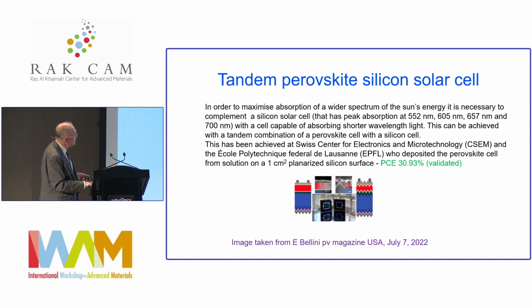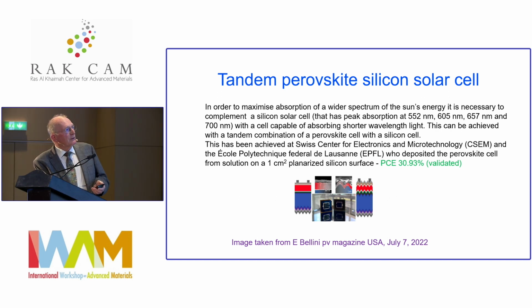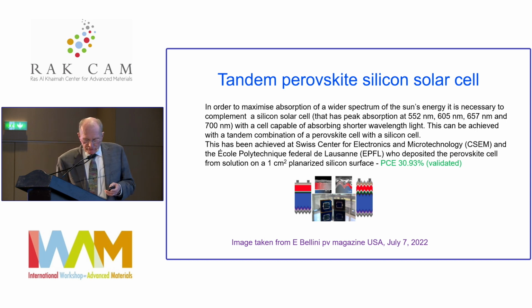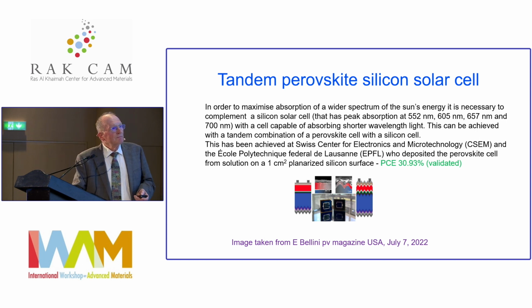And the Swiss center at EPFL in Lausanne developed a tandem perovskite on a 1 square centimeter planarized silicon surface and obtained a 30.93% efficiency, which has been validated. So that's a fairly impressive result for a small device.